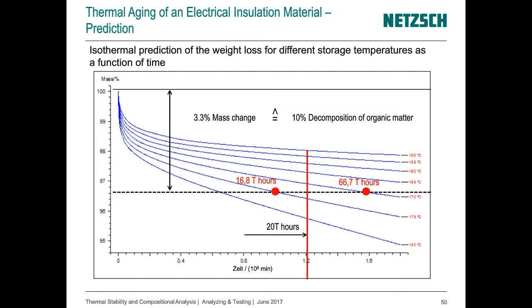And our prediction showed that it is possible with a storage temperature of 170 degrees C, then we get 66,000 hours as a result. But if we just go 5 degrees C higher, then this time interval is reduced to about 17,000 hours.